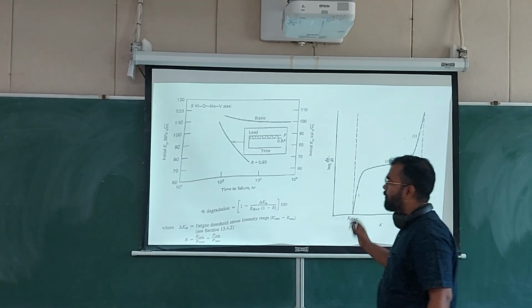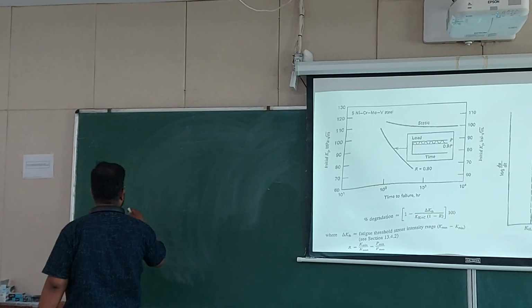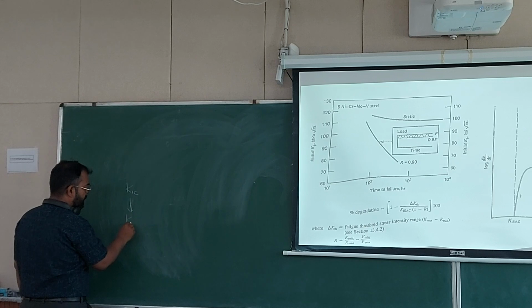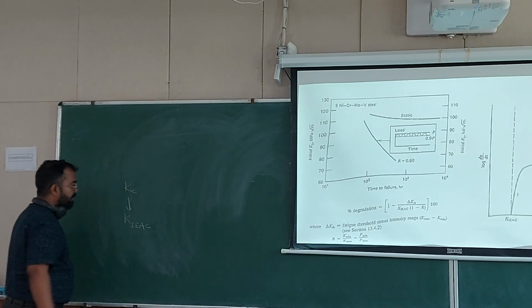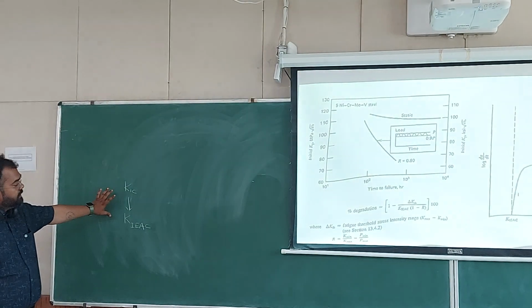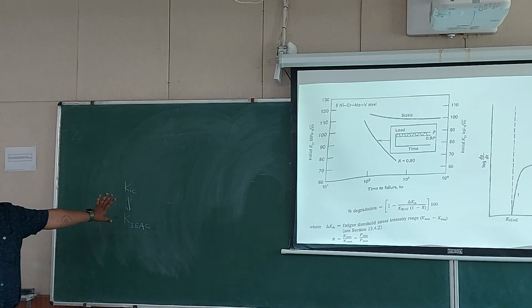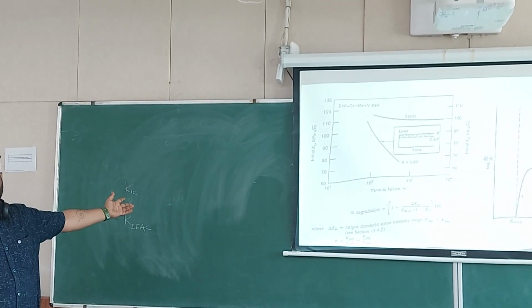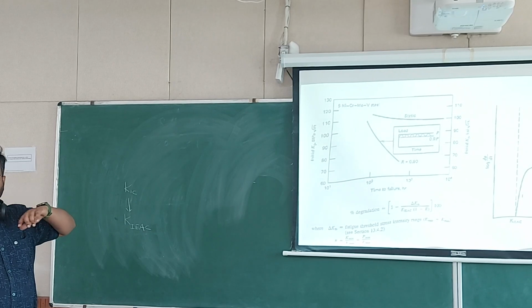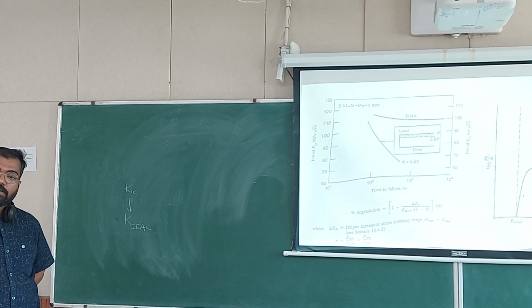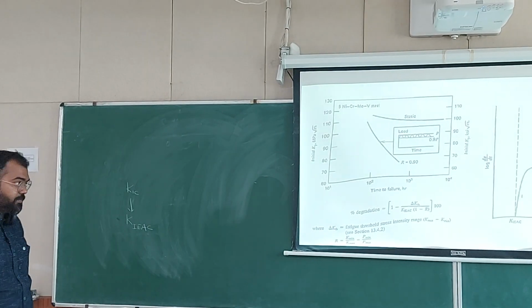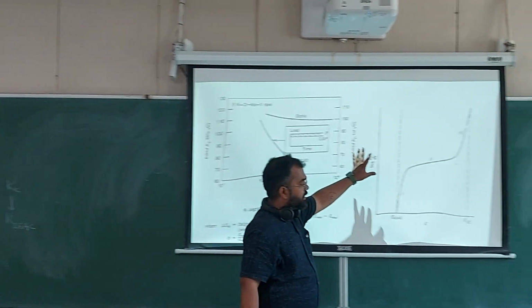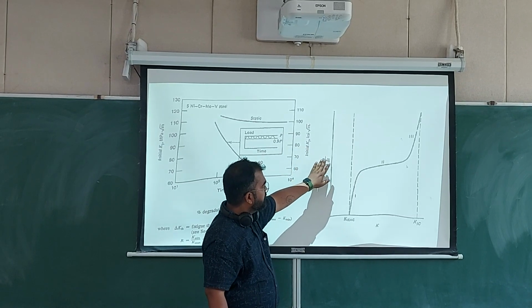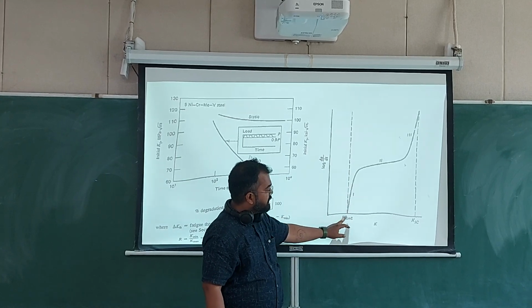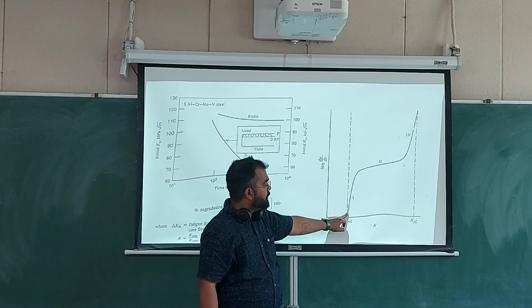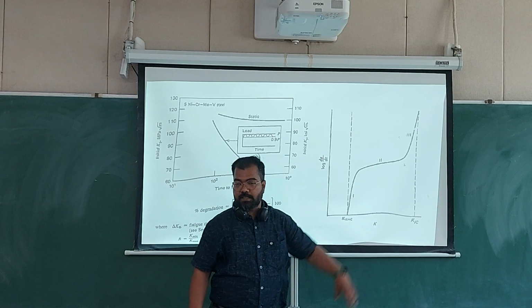What we have studied in the previous slide is that from K1C the value degrades to a lower value, which is K1 EAC, and between these two values the material can show stable crack growth. Once it reaches K1C, it will show catastrophic failure, and once it is beyond the threshold value of EAC, it will be stably growing. That's the plot on the right hand side, a double log plot of crack growth velocity versus K. For a certain value of K there will be no crack growth, then the velocity will increase, then it will become stable, and then unstable.